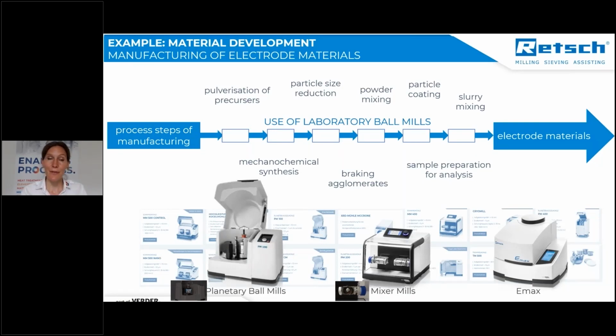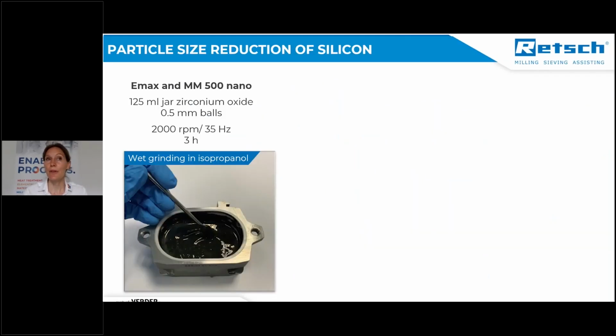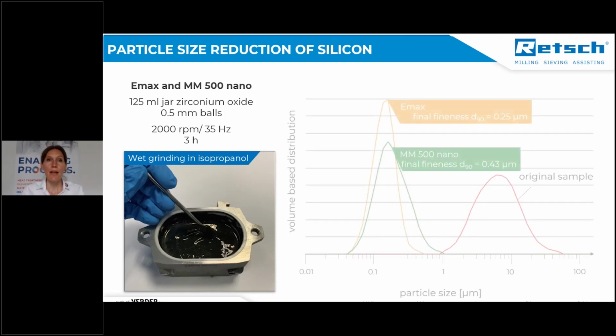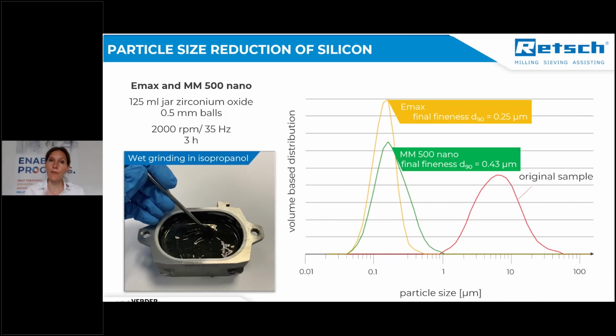So let's have a look at a specific application example, the particle size reduction of silicon. Silicon is an alternative anode material, and the task was to do nano grinding, so achieve very small particles. So we have to perform a wet grinding process. This is possible with Emax and MM500 Nano, in a 125 milliliter jar with very small balls at high speed for several hours. And this is a result. It was possible to shift the particle size down to, in case of Emax, a finest D90 of 0.25 micrometers. And in case of MM500 Nano, 90% of the particles were smaller than 0.43 micrometers.